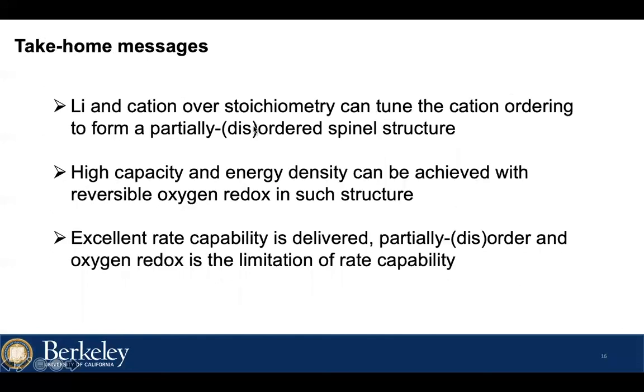To summarize my report, here is the take-home message. In this work, we apply lithium and cation overstoichiometry to tune the cation ordering and form a partially disordered spinel structure. This material can achieve high capacity and energy density using a large amount of reversible oxygen redox. Besides, we found this partially disordered spinel structure can deliver high rate capability. And we believe that the cation disorder and oxygen redox are not limiting the rate performance.